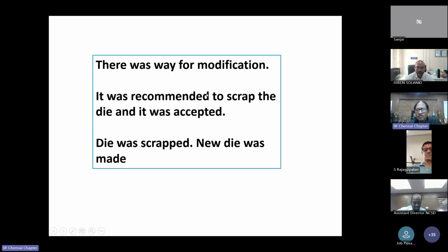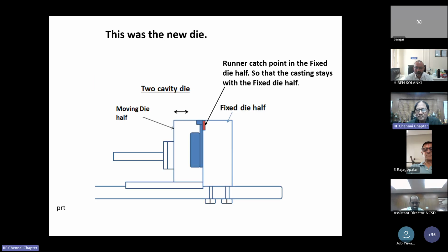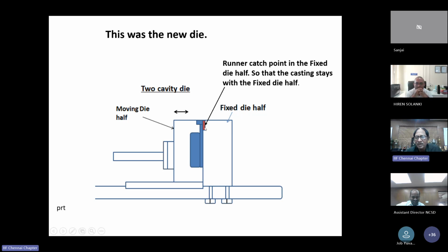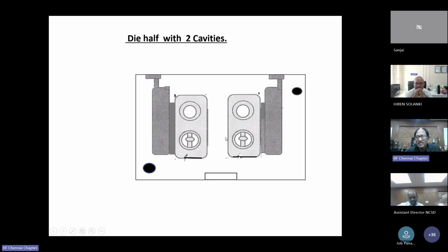There was no way for modification of the die. So I recommended the die to be scrapped and then there is no other way. It was accepted and a new die was made. This is the new die, simple die. This is one fixed die, very simple die. This is a moving die. This is operated by a toggle. This is die base. One is fixed here. And it is also a runner catching point. So the casting will not move, it goes with the moving die. Very simple construction. This is also a 2 cavity die pouring from the top.